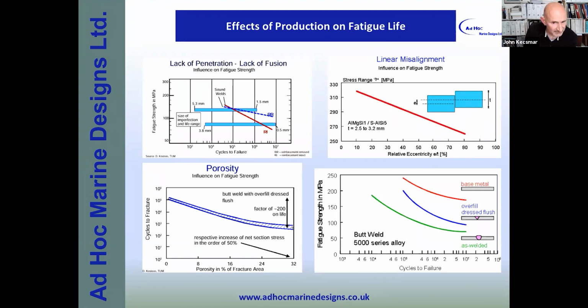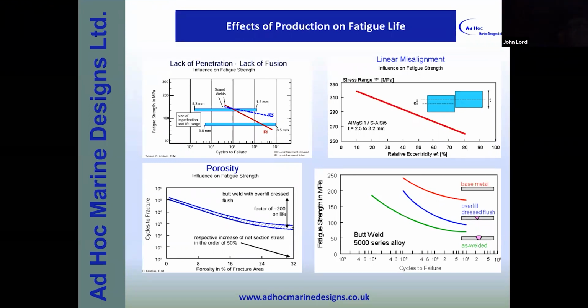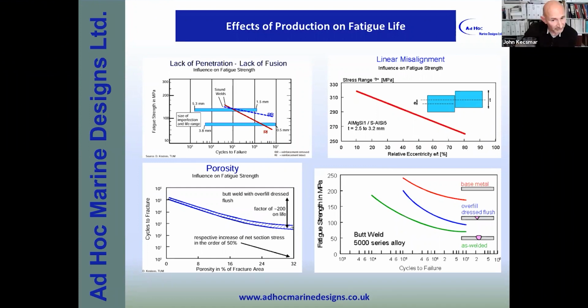Now, fatigue failure in aluminium is a voluminous subject on its own, and there's just simply not the time for me to discuss it all. However, what I can point out are some obvious issues. What we can see is that the larger and larger the weld bead, the more this reduces your fatigue strength, simply because you have a localized greater stiffness, relatively speaking, between the weld and the parent metal, just like the frame, just like your superstructure. So there's a stress concentration. Therefore, if you're over welding, you're actually making the situation a whole lot worse.